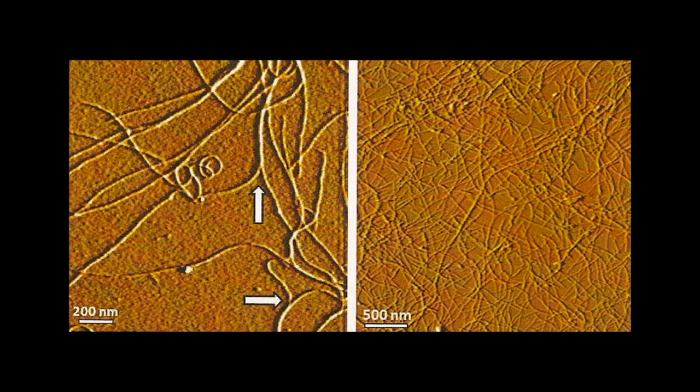The fibers also form complex structures. They wrap around each other and form double fibers and triple fibers. And the internal structure of the fiber changes somewhat. So we're interested in all of that. It also has potential implications in neurodegenerative diseases, particularly Alzheimer's disease. If you look at the neurons of people who have died from Alzheimer's disease, you find these amorphous plaques inside the cell and outside of the cell. And there are two different proteins. We're using a protein called lysozyme here, which forms fibers rapidly. It's a nice model for us to use. And the other proteins that are associated with neurodegenerative diseases also form these same kinds of fibers in a test tube, so in a thermodynamically controlled process.